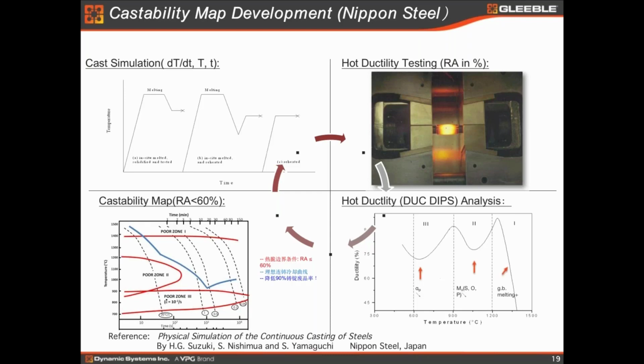When I was a PhD student at UBC, I was lucky enough to work for Dr. Keith Brimacombe, who was considered one of the pioneers in steel casting in the world at that time. He spent a tremendous amount of time studying how to design the mold to control the shell thickness of the steel. Because if you don't control the thickness evenly, then you generate thermal stress. And when you have thermal stress, I assure you that you will have cracks.